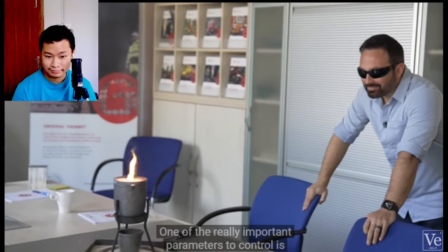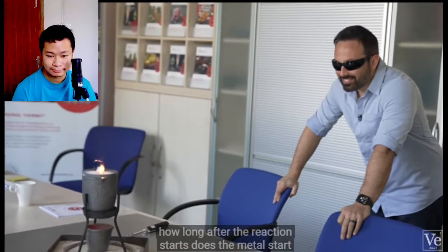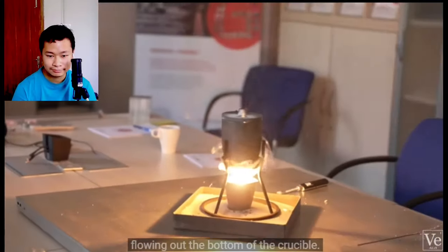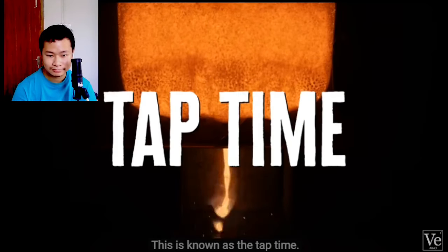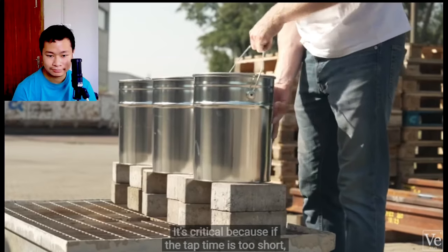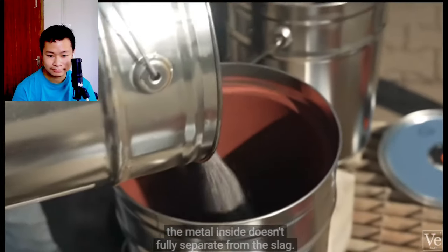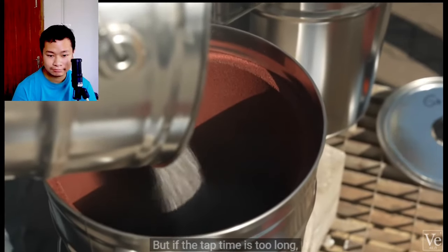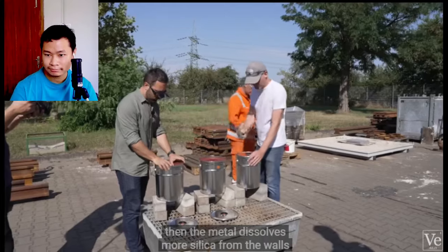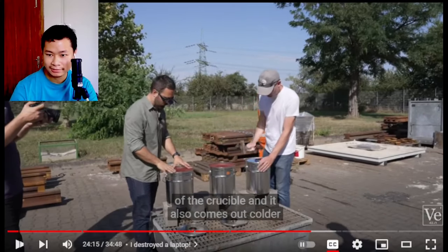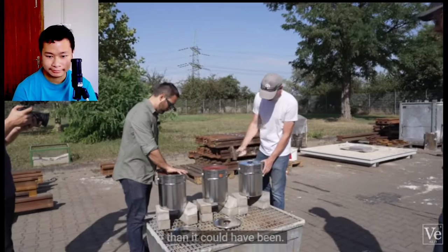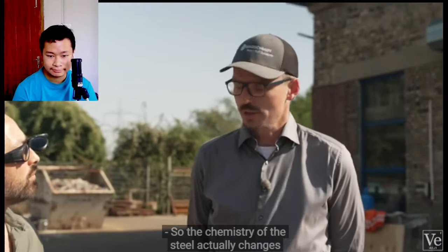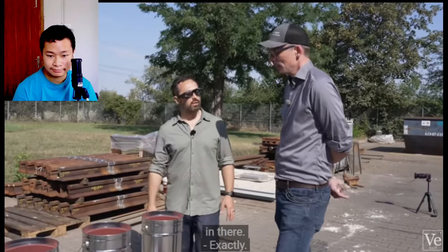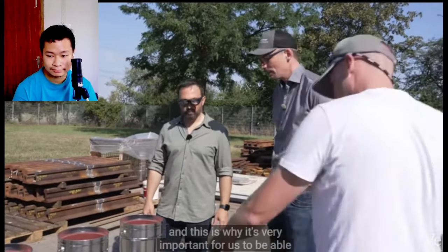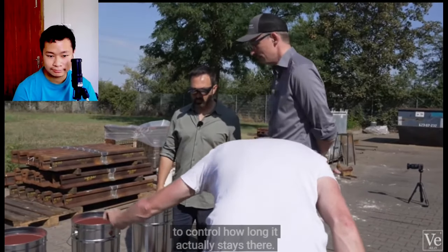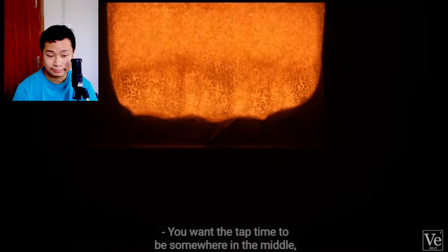One of the really important parameters to control is how long after the reaction starts does the metal start flowing out the bottom of the crucible. This is known as the tap time. It's critical because if the tap time is too short, the metal inside doesn't fully separate from the slag. But if the tap time is too long, then the metal dissolves more silica from the walls of the crucible, and it also comes out colder than it could have been. So the chemistry of the steel actually changes over longer time. Exactly. The longer it stays in there, and this is why it's very important for us to be able to control how long it actually stays there. You want the tap time to be somewhere in the middle, just right.